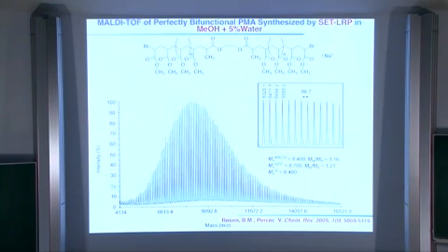You are looking here at the MALDI-TOF spectrum of a polymer made via this methodology, and this is as good as polymer chemistry is able to do today. It's called living radical polymerization. It provides polymer homologous species that have perfectly controlled structure of their chain ends.